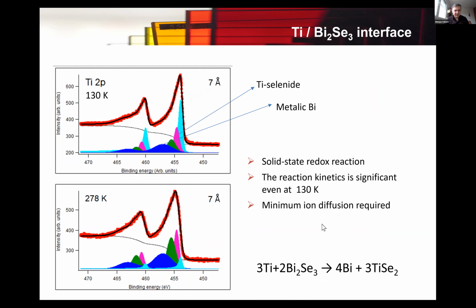But we were up for more surprises because we have done the same experiment at only 130 Kelvin. And we were able to confirm that this reaction is a solid state reaction, completely solid state, no liquid, no gases, products or reactants. This reaction also happens at 130 K, this cryogenic temperature. So that, to my knowledge, is the only solid state reaction I have seen that would occur so low.